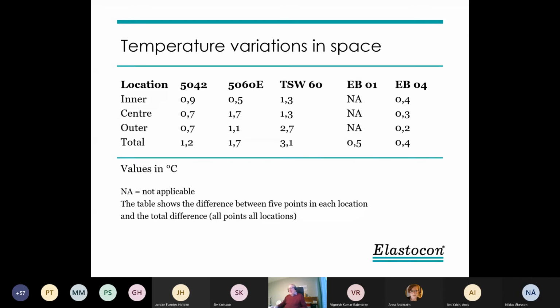But the other thing is the temperature variations in space. There we measured in 15 locations, but we could only measure 5 at a time. So we had a frame with temperature sensors in each corner and 1 sensor in the center. And that frame was then placed inside the oven 50 millimeters from the back wall, then moved to the center of the oven, and then moved to 50 millimeters behind the door.